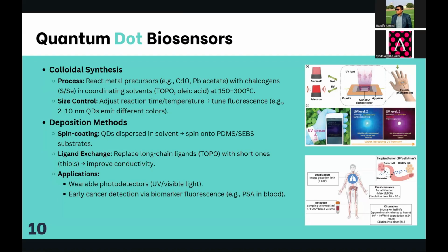So now let's shift our focus to quantum dot biosensors. How are these synthesized? The first method is colloidal. We mix metal precursors like cadmium oxide with chalcogens like sulfur or selenium in solvents like trioctylphosphine oxide at a temperature of 150 to 300 degrees Celsius. By tweaking the reaction time and temperature, we can control quantum dot size, which can vary from 2 to 10 nanometers. That determines their fluorescence color. The smaller dots emit blue colors, and larger ones emit red.